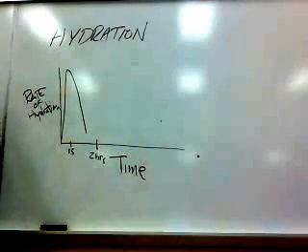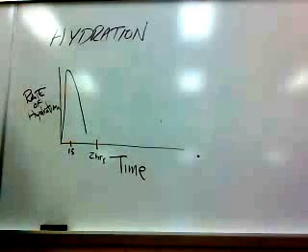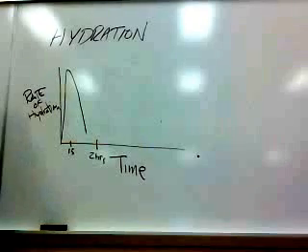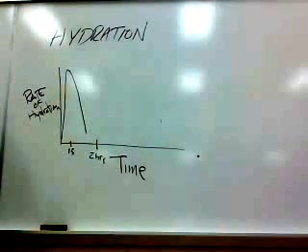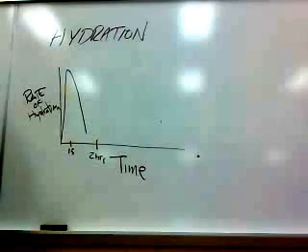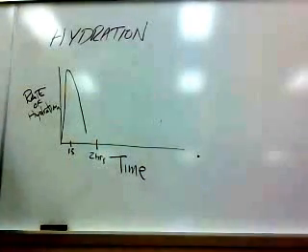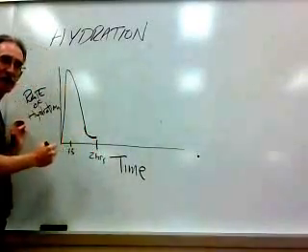But what's happening here is that the mix is starting to be flooded with calcium ions and other ions. The reaction's going onwards at a slow rate, but there are things that are starting to flood into the solution. After about 2 hours, that's when it all changes.